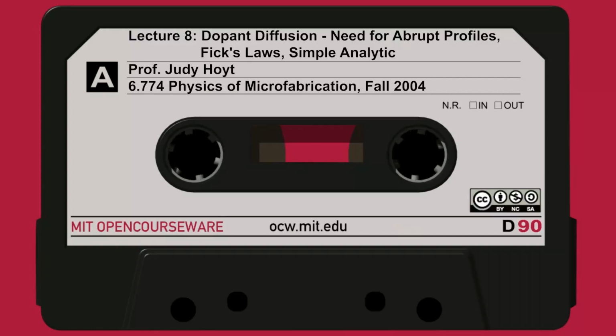Originally, in the early days, this pre-deposition step to introduce the dopants was done by diffusion of the dopants into the wafer from a doped glass, or by introducing into the silicon by heating in a doped gas ambient. The pre-dep is rarely done these days in that particular way. In more modern technology, it's usually done by ion implantation, which is a process that we're going to discuss later, and it's covered in detail in Chapter 8.